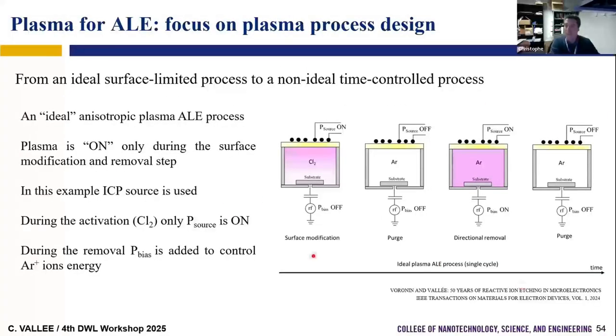So this is the basic ALE process we use with plasma. So we can do thermal ALE, but today I will not talk about thermal ALE, isotropic ALE. I will only talk about the anisotropic ALE because we talk about reactive ion etching, which is an anisotropic process. So for anisotropic ALE, usually we have two steps, surface modification and removal. You have a first step, surface modification. For example, we do chlorination.